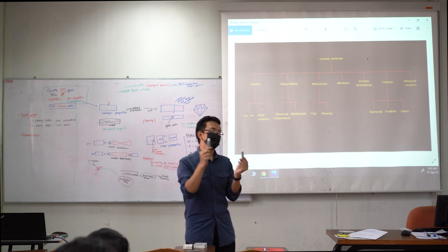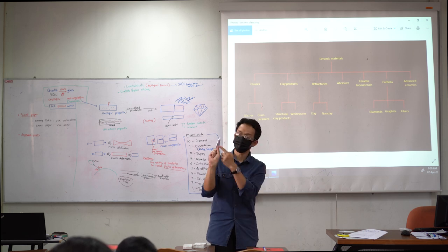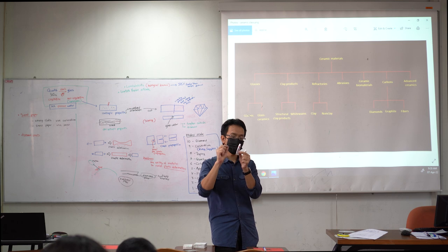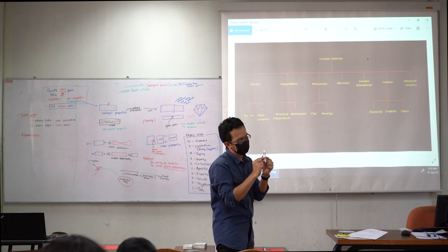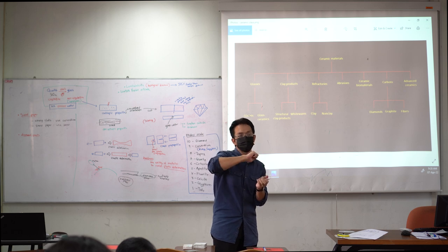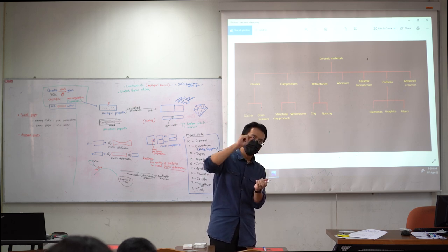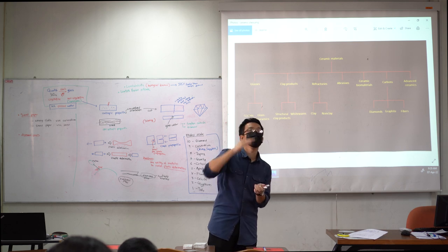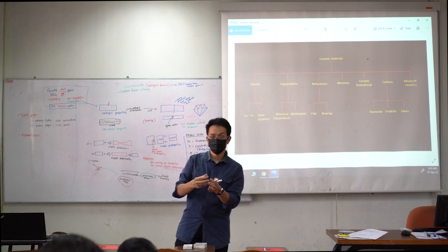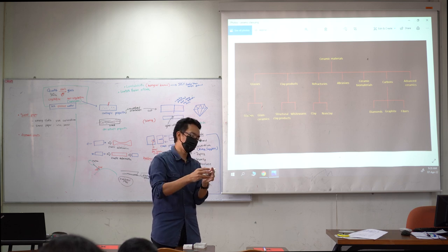So you can see on this diamond paste, there are numbers. Here it is 0.5, here it is 10, meaning it can go to a roughness of 0.5 micron. Meaning it can polish the surface to the point that the roughness is below 0.5 micron. So you can pass it along and see the difference between the unpolished one and the polished one. So they use a diamond paste.